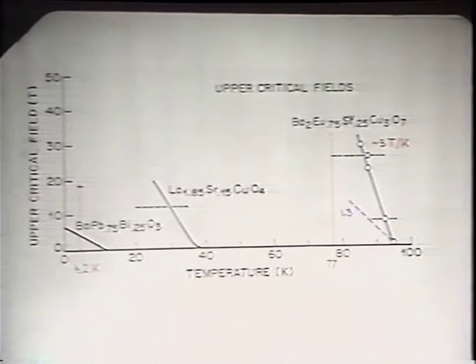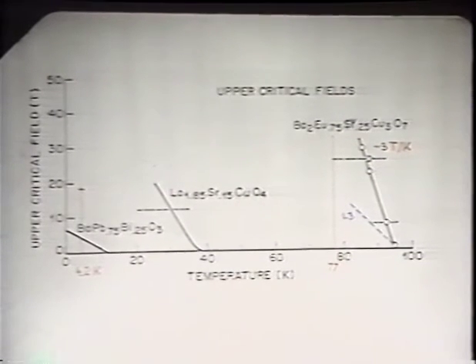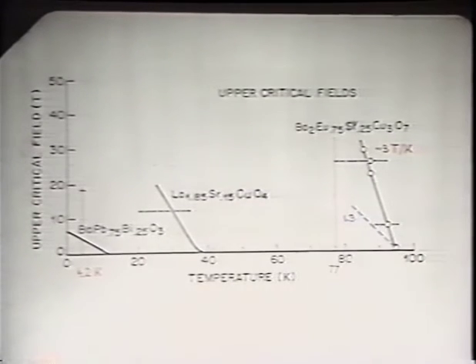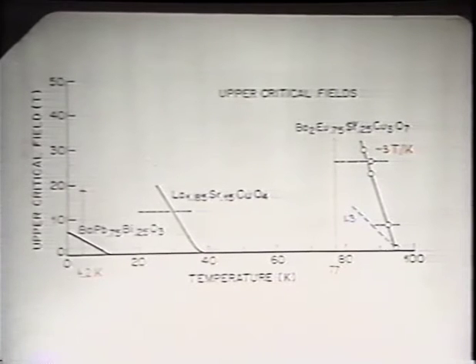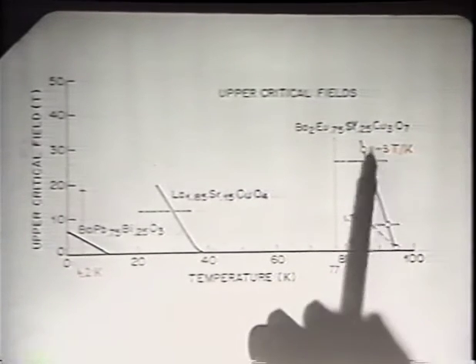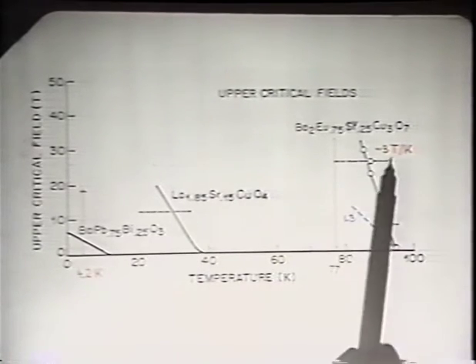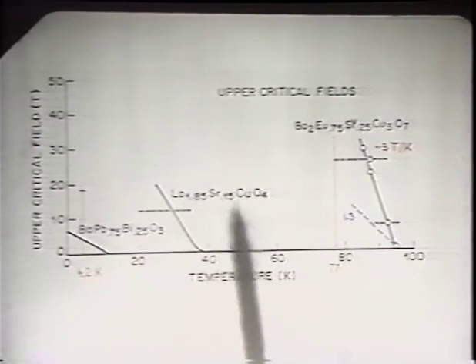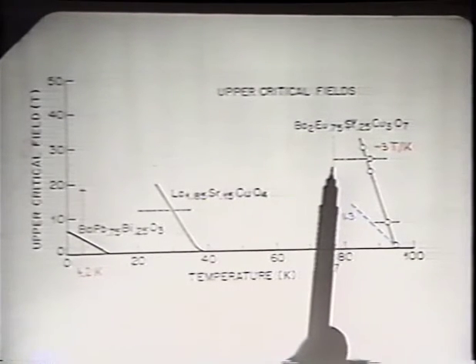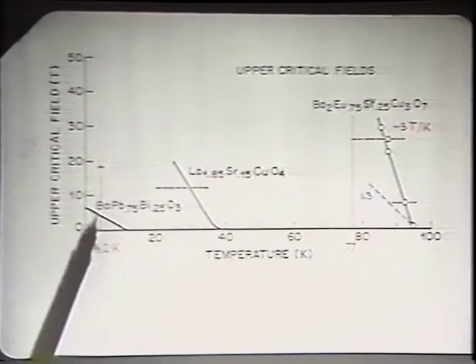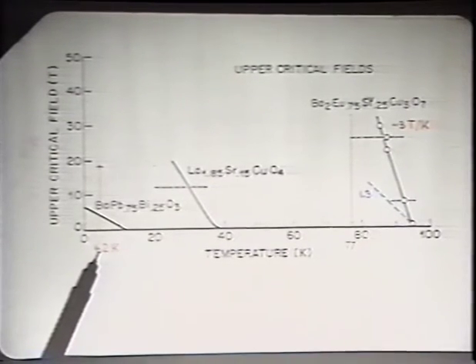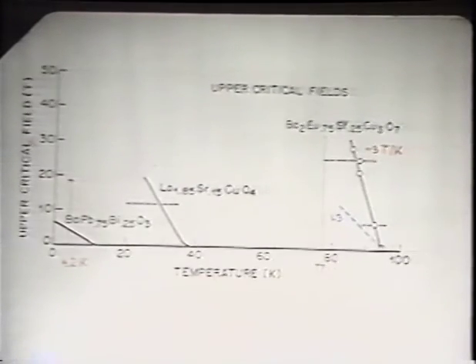That's not the point to make here. I think we should be somewhat conservative and say where the material goes normal, and that's indicated by the width of the bars, because the transition broadens in high fields due to the fact that one has anisotropic behavior. The anisotropy of the conduction state, very much like in the layer compound, smears the TC out. So if we were to make a magnet out of that, just in our minds, and operate it at 77 degrees, we would be able to operate it in a field range of, say, 20 Tesla or so, to be somewhat conservative. That is the same field as we get under best circumstances nowadays in our labs, and we are very proud to have these magnets that work up to 18 Tesla at 4.2 degrees. That's one aspect which I find fascinating. Do we have wires of that?